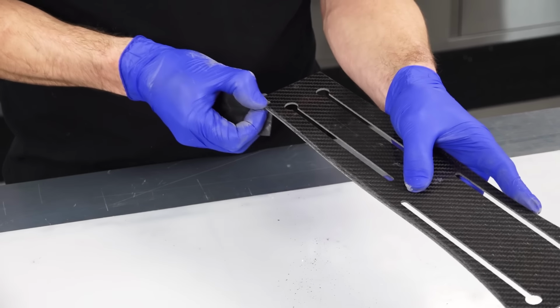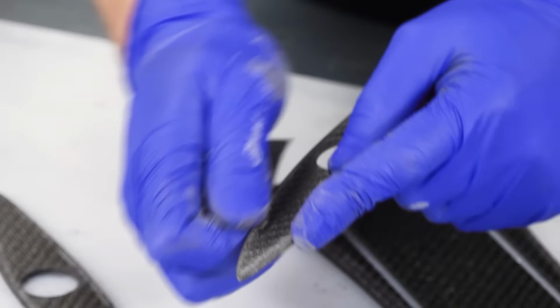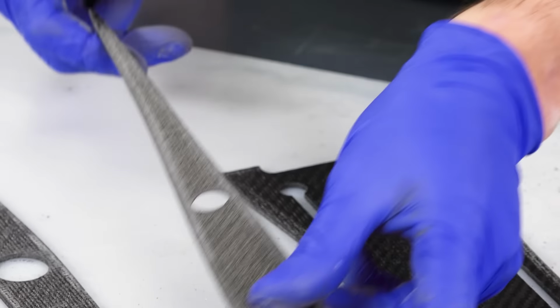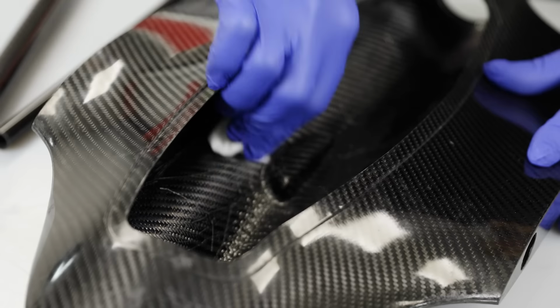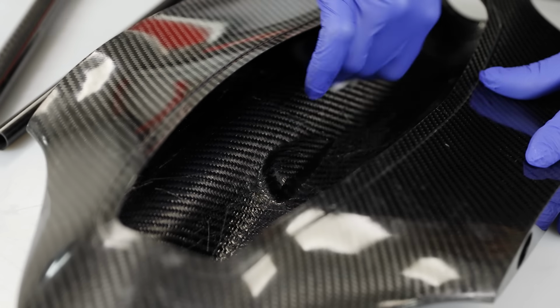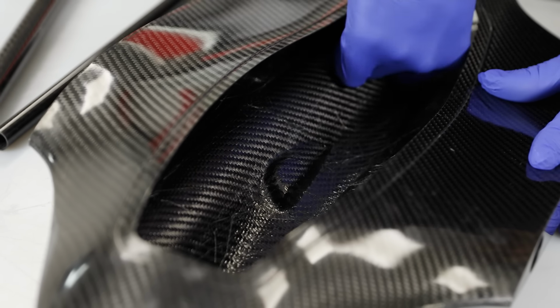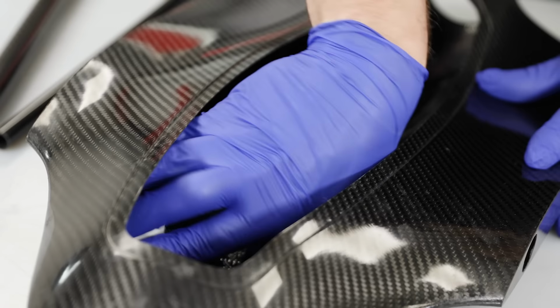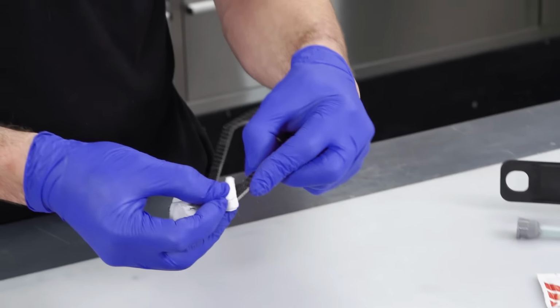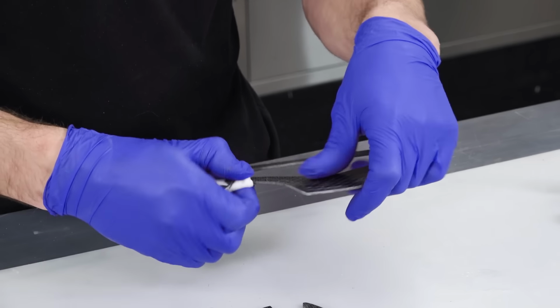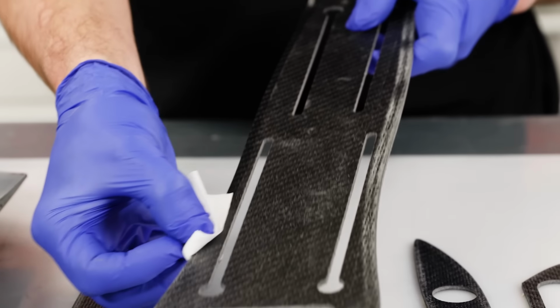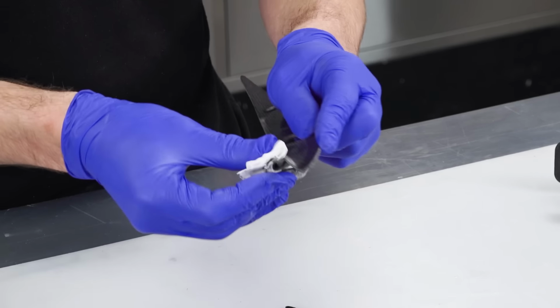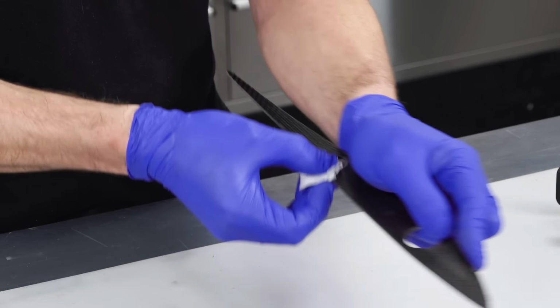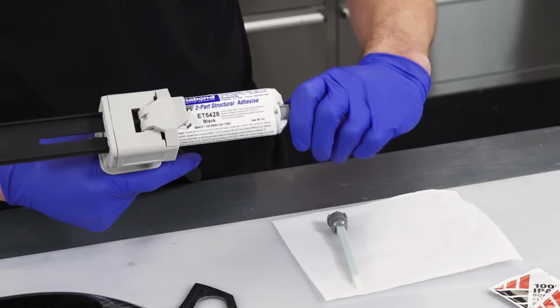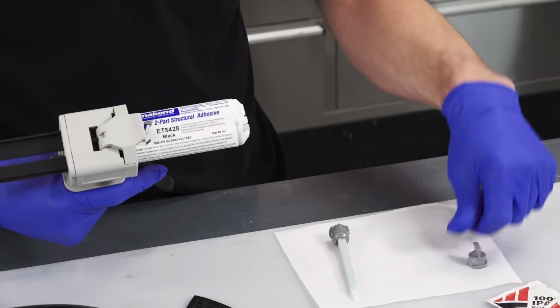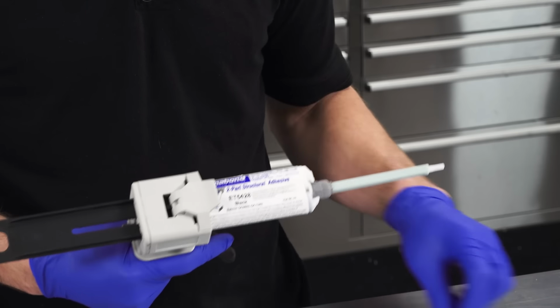I'm using a fairly fine 240 grit abrasive on these very thin materials, as it's important not to sand too far into them. Then just blow or wipe away the dust and degrease thoroughly using an IPA wipe. For bond preparation, 100% IPA is recommended as it's a more powerful degreaser and won't leave any residual moisture, particularly on porous substrates. Using a dispenser gun with a static mixer nozzle, the adhesive can now be applied.